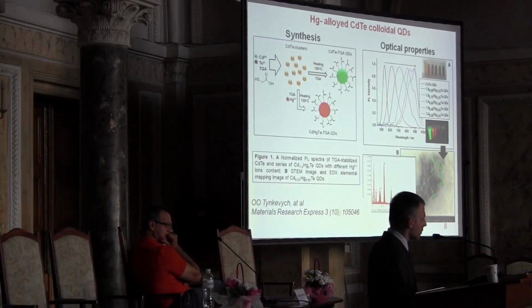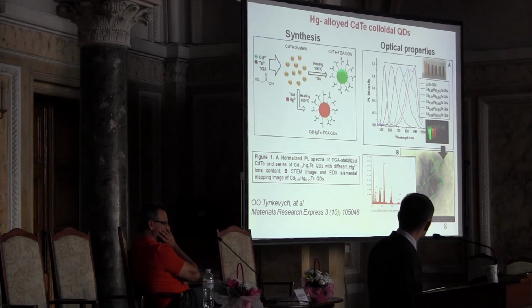This is a really simple chemistry approach. So the example of this alloying with mercury gives us the opportunity to first shift the luminescence peak to the near infrared region. Like you can see here, they become broader, several peaks appear here, and if you also study it electrochemically, and with electron microscopy, you see that the size of the initial particle basically does not change so much during the alloying, but only the changes of mercury content change these properties very much.